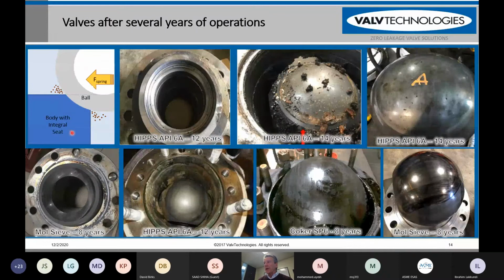Here are some of ValvTechnologies valves that have been in service in different severe service applications for a period of time. You can see this valve right here was used as a HIPPS valve. It's an API 6A valve, and it was in service for 12 years. After disassembly, after a shutdown, the inside of the valve still looks perfect. Here's one of our balls that has also been in a 6A HIPPS service for 14 years. Although there's a lot of debris, the valve has special construction and is coated with TCC, tungsten carbide coating, or chrome carbide coating, and the seating area is still beautiful.